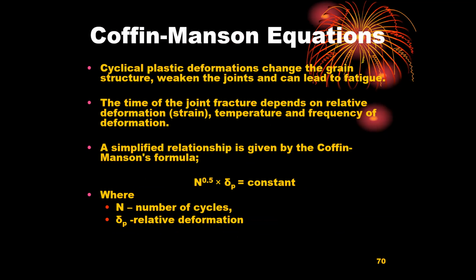So cyclical plastic deformations change the grain structure or weaken the joints, and then they can lead to fatigue. The time of the joint fracture depends on relative deformation, strain, temperature and frequency of deformation. So a simplified Coffin-Manson relation would be the number of cycles to the root multiplied by the relative deformation of the plastic strain, and that will be a constant. As fatigue goes by and embrittles the structure, giving less and less plastic strain, there are a few issues.